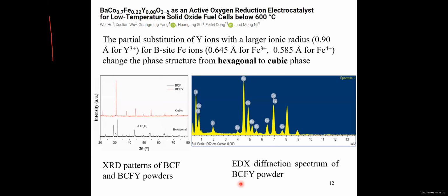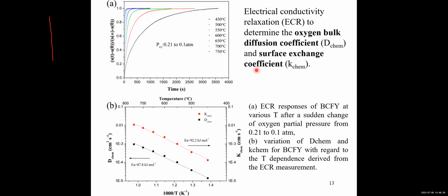Also, in the past few years we tried to dope the B site with some larger ions. For example, partly replacing iron with Y ions, because the Y ion is much larger than iron. So we successfully transformed the hexagonal phase into cubic phase, which can give us much better electrochemical performance.